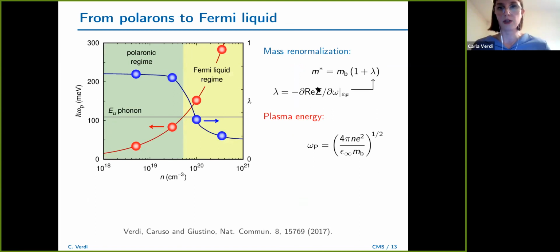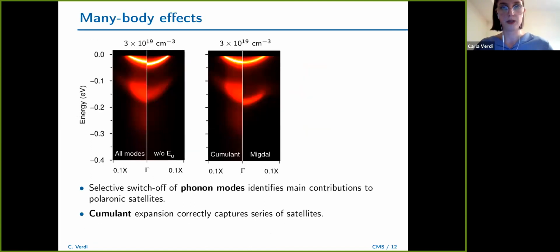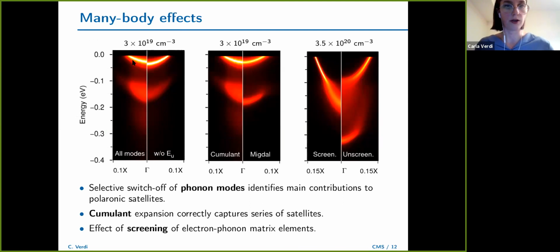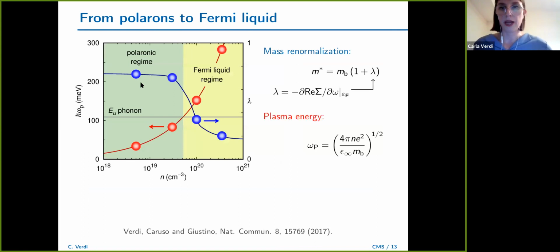The mass normalization is calculated either from the derivative of the real part of the self-energy at the Fermi level, or you can do a parabolic fit of the bottom of the conduction band, or a linear fit near the Fermi level. This will give you the mass normalization, and the two estimations are absolutely equivalent. The plasma energy instead is estimated from the electron gas model, but you can also calculate that directly from first principles if you want, and we did verify that. It's just quite lengthy to calculate. You can calculate the electron energy loss function. You take your crystal, you insert some extra electrons, and you calculate the dielectric function, and you look at which energies are the peaks of the electron energy loss function. The low energy peak will correspond to the plasma energy that I'm talking about.